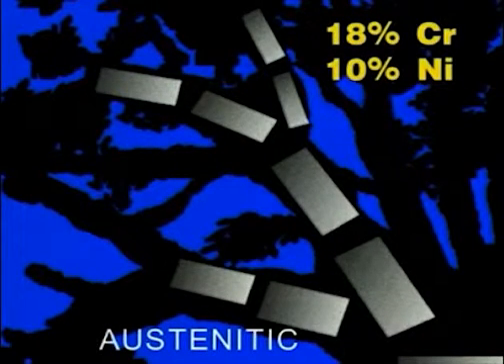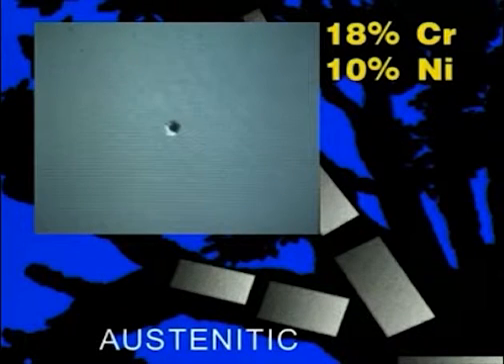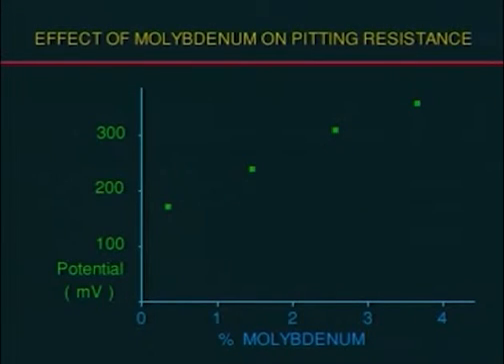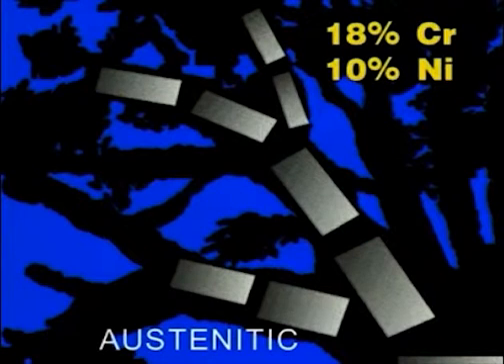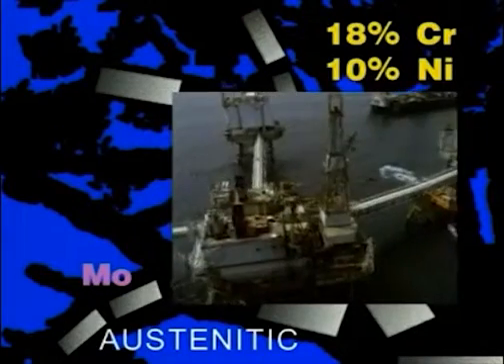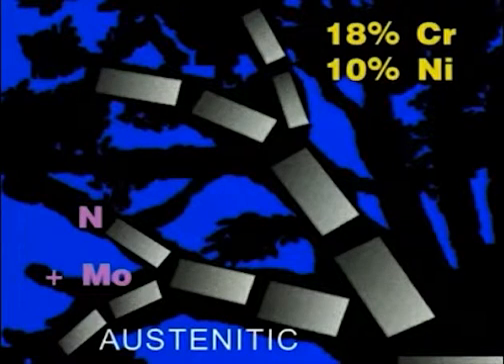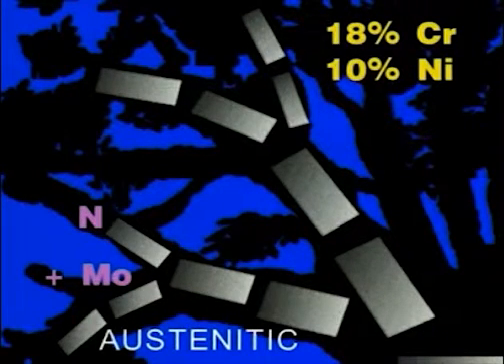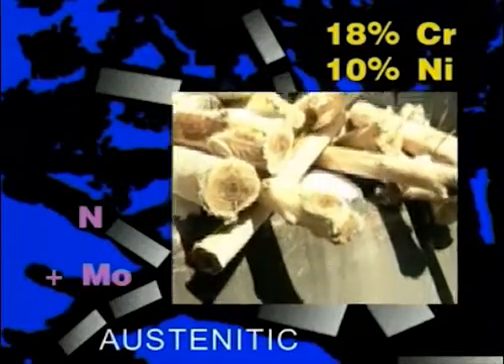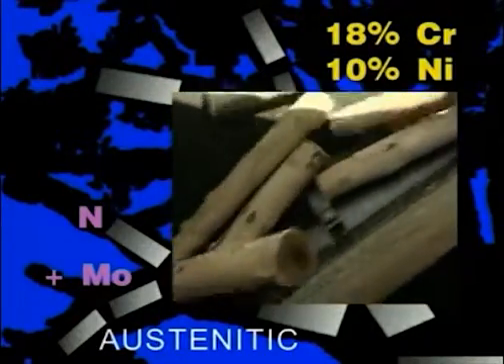Although chromium-nickel stainless steels have good resistance to general corrosion, they are susceptible to pitting by salt water, chlorides and similar elements. However, adding molybdenum greatly increases the steel's resistance to pitting corrosion. So stainless steels containing molybdenum are specified for this environment. Adding more molybdenum and some nitrogen further increases the steel's resistance to pitting corrosion, making it suitable for the very aggressive environments encountered in paper pulp production.